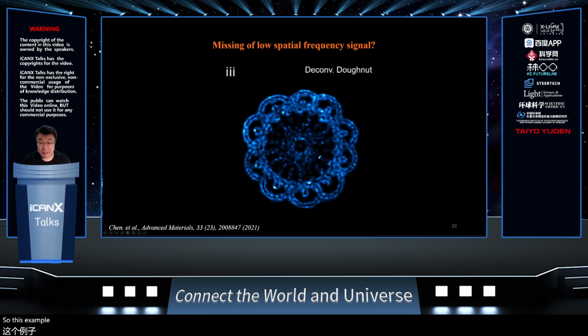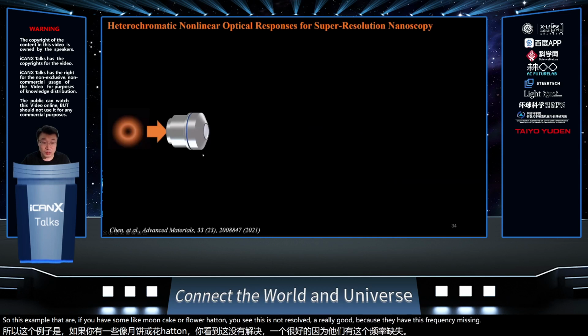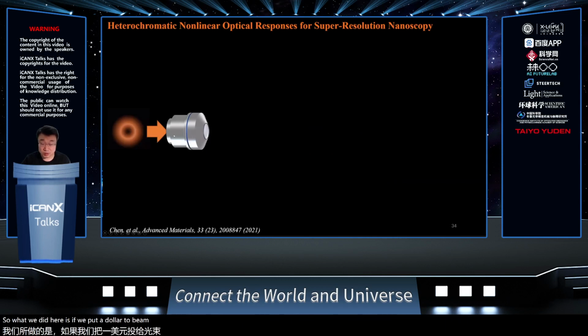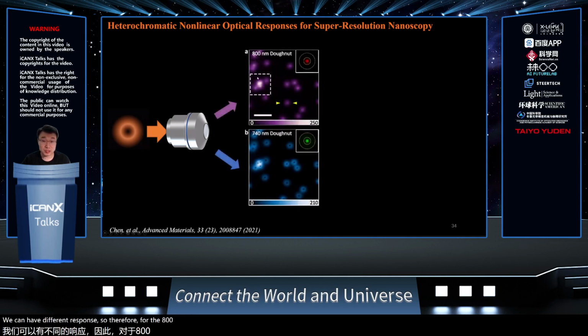This is an example: if you have a mooncake or flower pattern, you see this is not resolved well because of the missing frequency. What we did here is put a donut beam into our system. Because for nanoparticles at different energy levels we can have different responses, for the 800 nanometer emission we basically have a Gaussian emission because they are already saturated. And for the 740, which is also near-infrared emission, you have the donut. So if you look at the Fourier domain, the 740 is good at the larger frequency range, and the 800 one is good at the lower frequency.